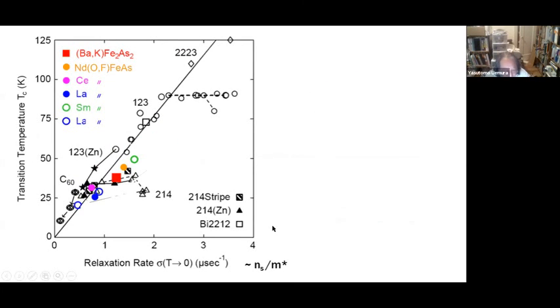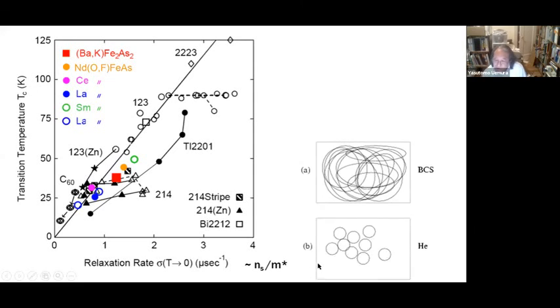Okay, then we added many data, as perhaps you know, on different unconventional superconductors doing similar measurements. And here we show the results of iron arsenide and buckyball superconductors, K3C60 or other alkali A3C60 here, and also the overdoped side of the cuprates. So in all these cases, we see an approximately linear correlation between Tc and the superfluid density, which is quite interesting.